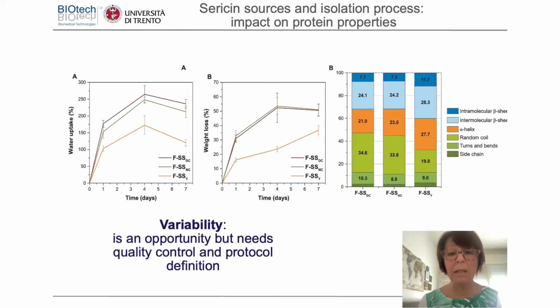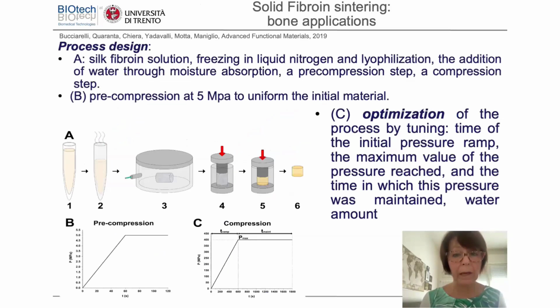And different chemistry means a different ability to assume a different conformation. For example, this is related to sericin isolated from different sources again. Because of the different chemistry, if you look at this histogram and consider, for example, the alpha helix conformation, depending on the source, the sericin can assume different crystalline degrees, but also different conformations, increasing alpha helix or increasing random coil. This means changing the hydrophobicity, hydrophilicity, but also the functionality and the impact on cellular behavior.